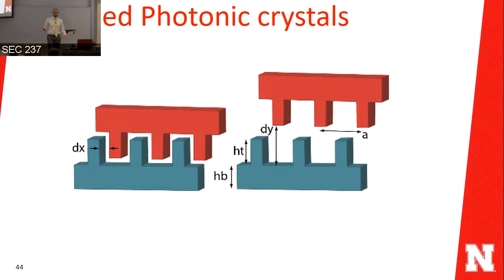So from any engineer's intuition, you can say that, okay, the heat transfer here will be multiplied by the surface area. That's true if thermal radiation is a surface phenomenon. This is true when the structure size is larger than the skin depth or the penetration depth of radiation. The penetration depth is around 10 microns only. So if you have structures that are smaller than the penetration depth, smaller than 10 microns, then you cannot just deal with thermal radiation as a surface phenomenon. You need to take into account the wave nature of radiation. You need to solve this problem truly and take into account the scattering between the two structures.